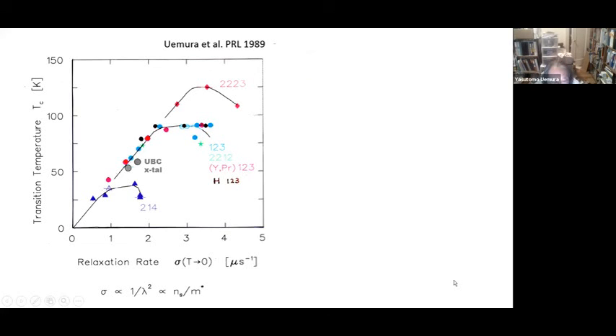So we started the study of high-Tc cuprate superconductors by MuSR by measuring the magnetic field penetration depth, 1 over lambda squared, that corresponds to the superfluid density n_s over m star. So what I'm plotting here is the transition temperature on the vertical axis and the lowest temperature approximate value of the superfluid density determined by MuSR penetration depths. And so these are each different specimens, and this is 214, 123, and 2223.